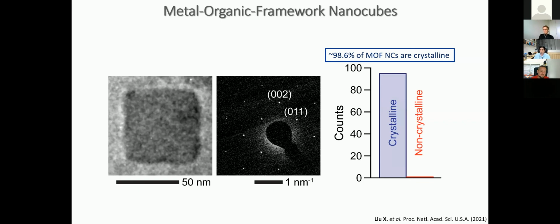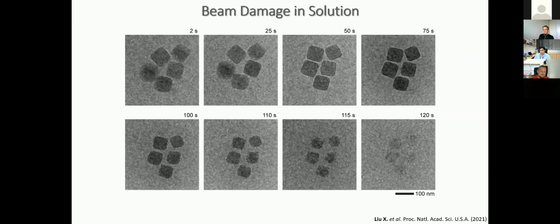So that's what we're gonna do. We're gonna use this. And we also looked at the effect of the beam very quickly. Okay, so we pre-synthesize them off, we put them into the liquid cell under the liquid condition, and we start imaging. And what you see, at 120 seconds, they're disappearing. So this tells us, okay, what is our working window? How much dose we can put in, or how long we can do those experiments.